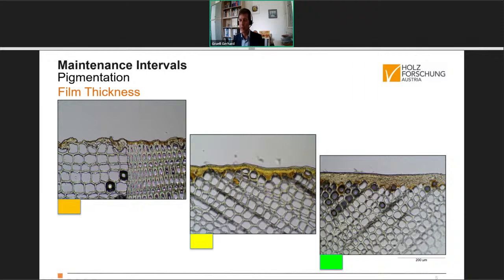And this is independent from the pigmentation I've shown earlier, because all these systems exist in opaque as well as in semi-transparent coating systems. And we estimated that the higher film thickness has higher durability. That's why it's green here. And the lower film thickness has lower durability. That's why it's orange. And the medium build are somewhere in between, of course.